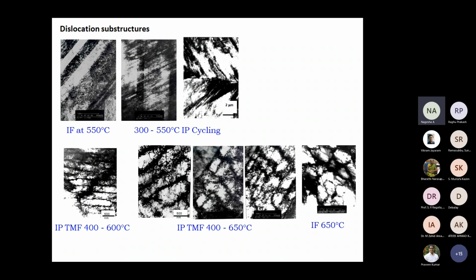So this is reflected generally in the form of planar, widely spread planar slip bands in this alloy. But as temperature is increased, the tendency for cellular dislocation structure increases, cross-slip happens, and this leads to the formation of dislocation cells, which is seen at higher temperature TMF, and also under IP-TMF cycling.